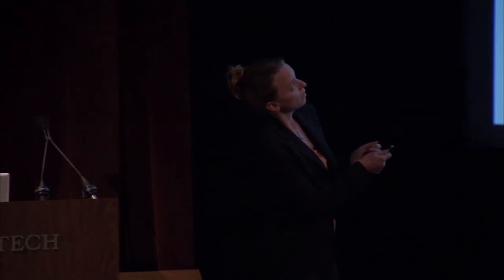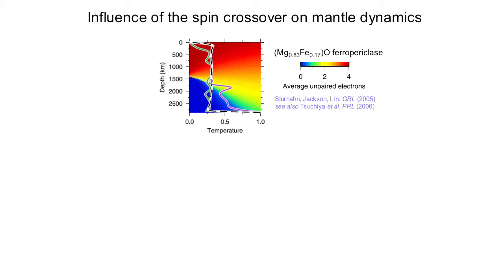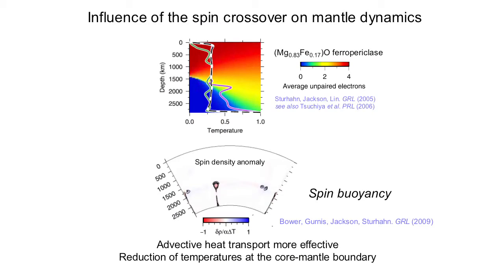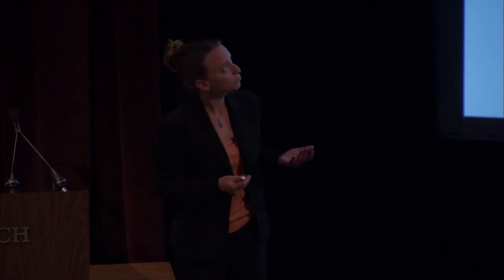So how does that density change with pressure and temperature due to this transition? It's in fact a very broad transition. This colored map shows the red are all of the iron states in this very buoyant case. It's a high spin, it's very buoyant, compared to its low spin counterpart, which is the area all in blue. But then as soon as we follow a mantle temperature profile, which are depicted in these different lines here, we see that it samples a region where the crossover is characterized as a broad crossover. That's why it's in fact not called a transition.